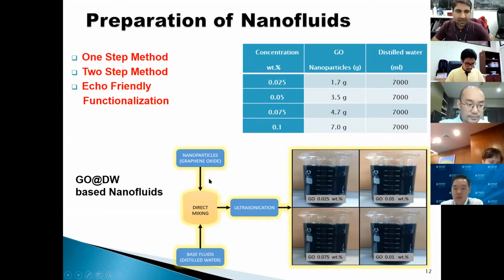So here we have the graphene oxide nanoparticles and base fluid water, then direct mixing by using ultrasonication, by setting different parameters like pulse time, probe temperature, amplitude, and on-off time. There are a lot of parameters that have to be adjusted here. Finally, we got the 4 different weight concentrations of GO and distilled water-based nanofluids.